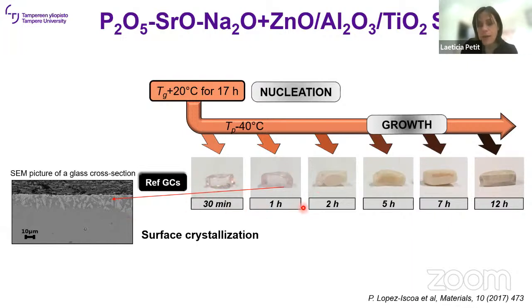So this is an example. So this is the reference glass, so the phosphates, strontium, and sodium. And you can clearly see that we have this surface crystallization and we have this amorphous part in the center, in the volume of the glass. And then we use a scanning electron microscope to confirm that we have surface crystallization, so the crystals are growing from the surface. So as I said at the beginning of this presentation, we want the crystals to be in the volume of the glass. So this is not the way to go to try to increase the spectroscopic property of the glass.